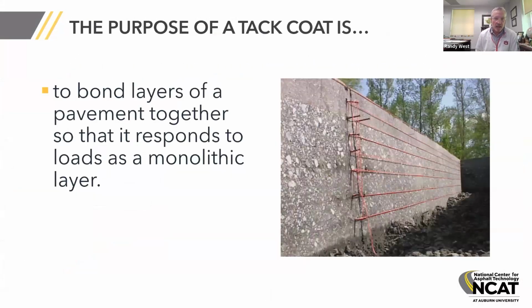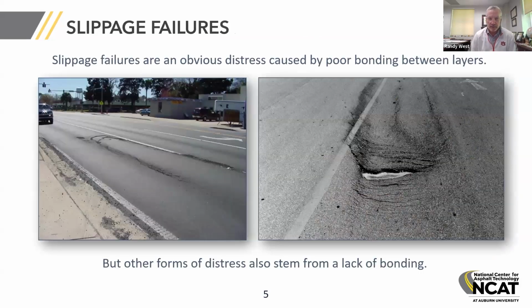We want the pavement to act as a monolithic layer. For years we've said building an asphalt pavement in layers is an advantage for our industry. But if those layers do not bond well and we don't have them behaving as really a single lift, then we're going to have trouble in terms of the pavement performance. As Nathan mentioned, slippage failures are an obvious distress caused by poor bonding, associated a lot of times with braking, could be acceleration as well, but there are other forms of distress that also stem from a lack of bonding.